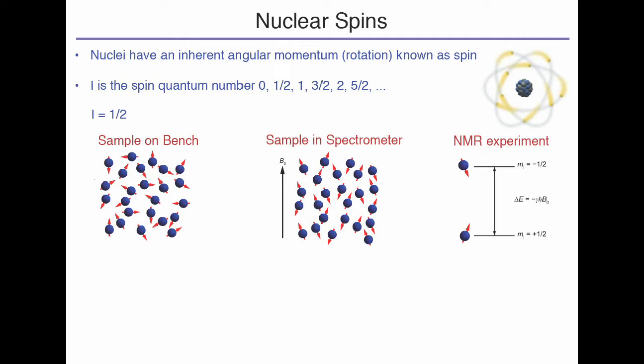If I had my sample just sat on the bench like this, then my spins are completely randomly oriented in all possible directions because I haven't done anything to the sample yet. If I want to do NMR on my sample, I put it into what's known as the spectrometer, which I'll show you a picture of in a second. The spectrometer contains a very high magnetic field strength. I place my sample into the magnetic field, and as soon as I do that, I've defined a field of magnetization. That dictates whether the spin is going to align with the field or against the field. You can see here my spins are now no longer randomly oriented. They're either up or they're down. These spins will have different energies depending on if they're up with the field or down. If they're aligned with the field, they'll be in the lower energy level, and if they're against the field, they'll be in the higher energy level.